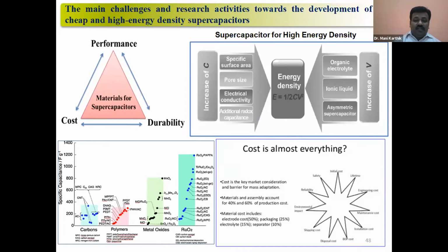But if you see the energy density, E = CV², we need to increase C as well as V². Your energy depends on the capacitance as well as the voltage. To increase the capacitance, of course, we need the specific surface area, the pore size, very good electrical conductivity of the material, and additional redox capacitance. For V², as I said, with organic electrolytes, ionic liquids, or asymmetric supercapacitors, you can increase the V. If you increase both, your energy density increases. So these are very key parameters. People look at how to modify their materials to increase the energy.